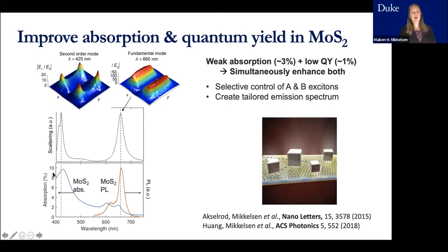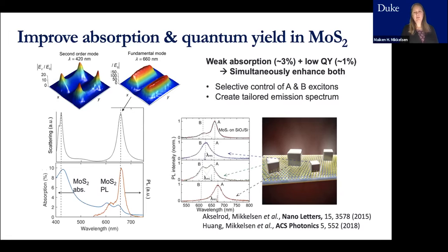And the second order mode allows us to enhance the absorption. And in addition to enhancing that, so that allows us to see enhancement around 2,000 times in the A exciton emission. So this top panel shows the intrinsic spectrum from monolayer MoS2 on silicon dioxide, a native substrate, and it has an A exciton here and it has a weaker B exciton. But what we found is by changing the size of the cubes, we can completely modify how this fluorescent spectrum looks. So we can mainly enhance the B exciton or the A exciton, or we can enhance both, depending on where we pick the plasmon resonance to be.